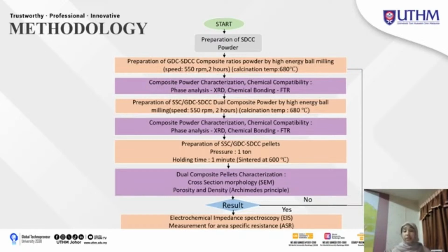Next, after getting the results, I'll go through the electrochemical impedance spectroscopy, EIS, and also measurement for area specific resistance, ASR. So EIS is a tool for breaking down total electrolyte impedance into various components of the cell. And ASR represents the ohmic resistance calculated from values of the symmetrical cell, and here there will be a bit of calculations to get the value.